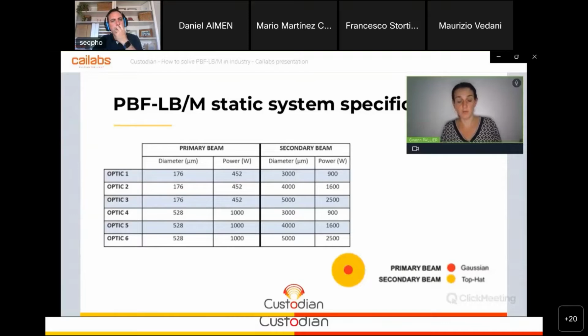At the same time, we wanted to try different sizes of the secondary beam. So we have tried 3 mm, 4 mm, and 5 mm diameter with both combinations of the primary dimension. At last, we also wanted to try different power ratios. So we have managed to tune the power within one of the shapes relative to the other in order to see what is needed in each case for the melting and for the management of the thermal gradient.